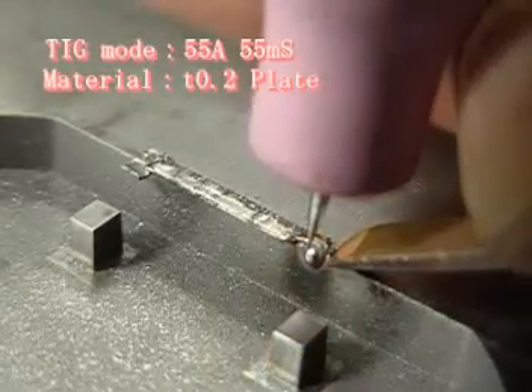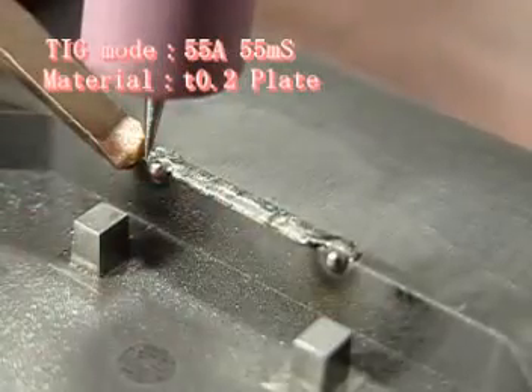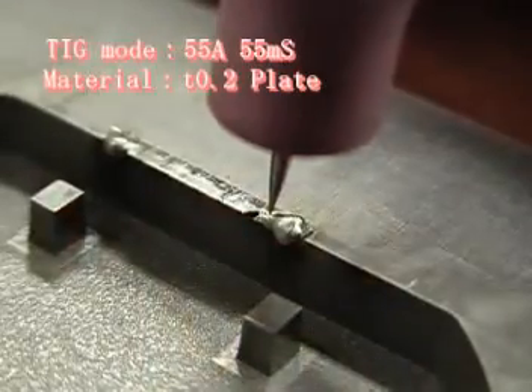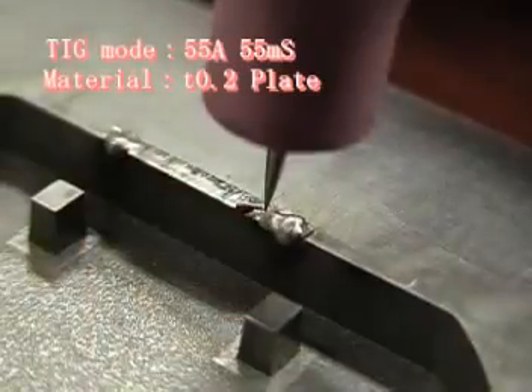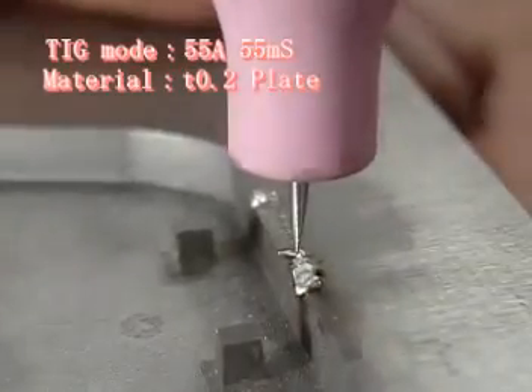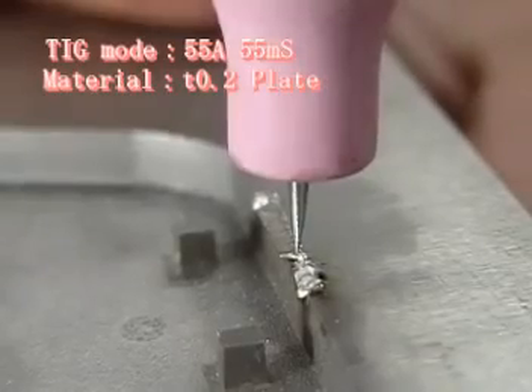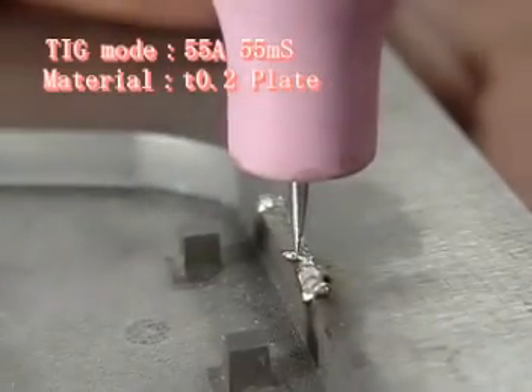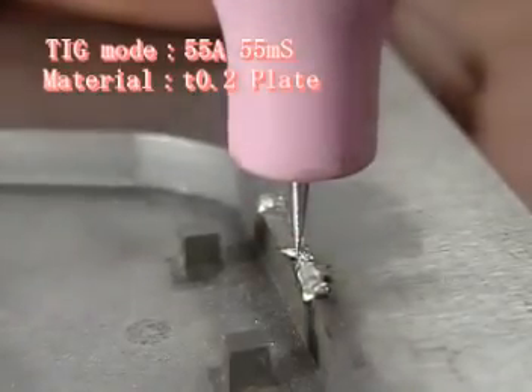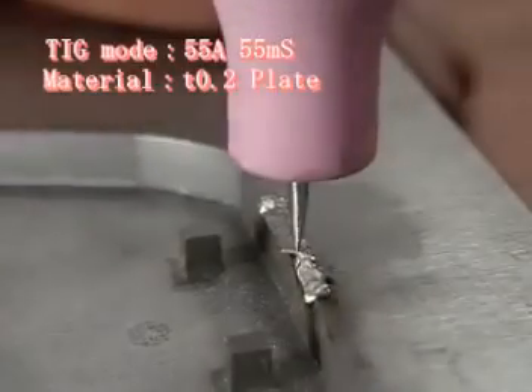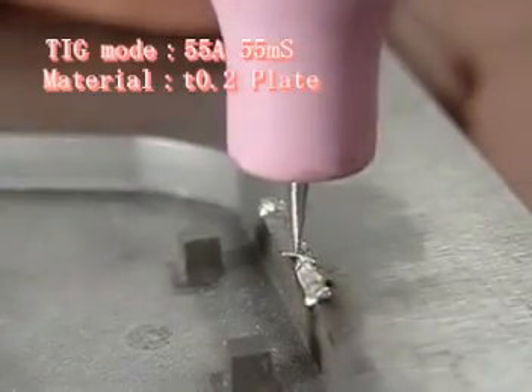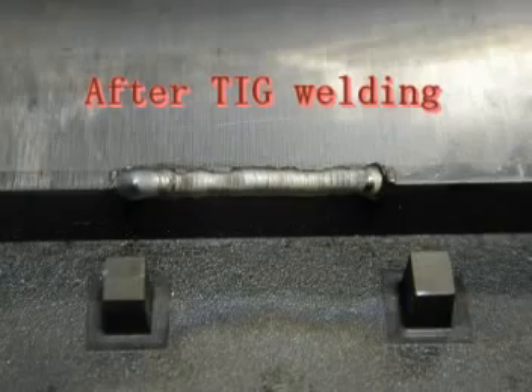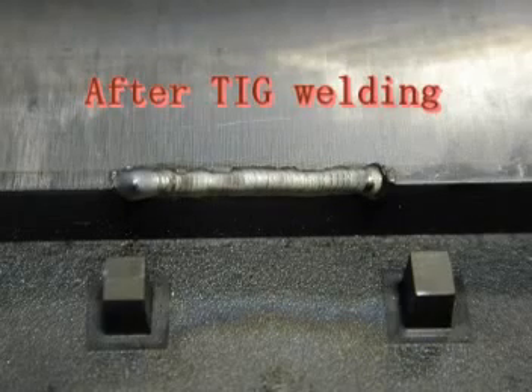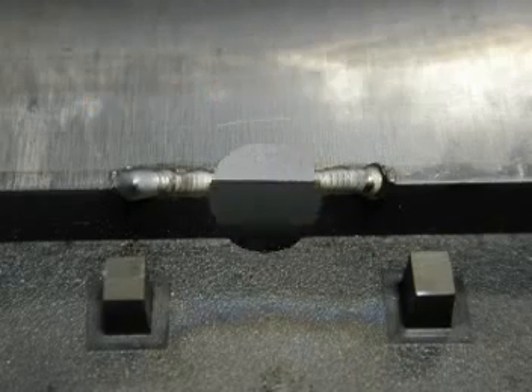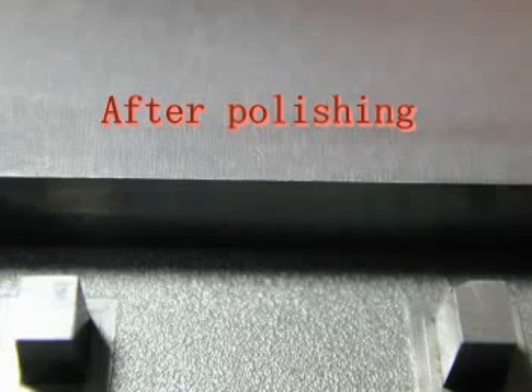Make a clearance of around 1.0 mm between the electrode and the welding material, and start melting down both ends. After melting down both ends, melt the middle part of the material. In this operation, move the electrode slowly to overlap the weld bead slightly. Avoid moving the electrode too much, which results in an uneven welding surface. In this way, you will have a perfect welding surface. Confirm that there is no shrinkage or parting lines.